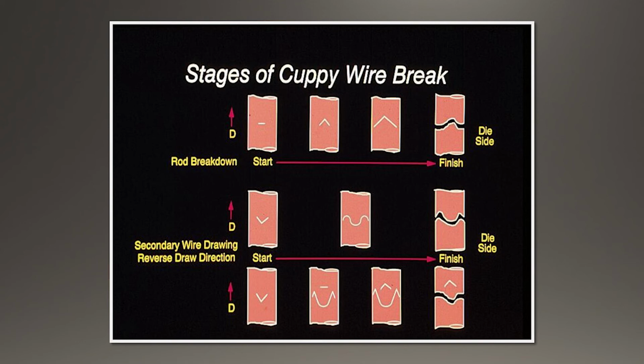Now, what happens in a wire rod breakdown machine? When you take that process wire and put it into the secondary machine, it's going to be drawn in the opposite direction. So this is now what that wire would look like in the secondary machine. There's a crack here, but it's going to increase as you draw it down. And if it breaks in the secondary machine, you'll have a cup end pointing in the direction of wire drawing. So it would be different than what took place if it happened in a rod breakdown machine.